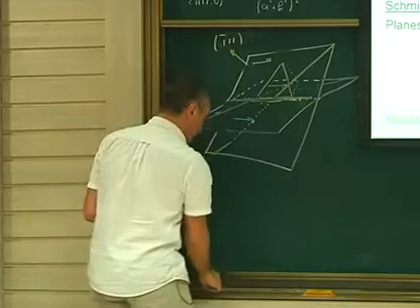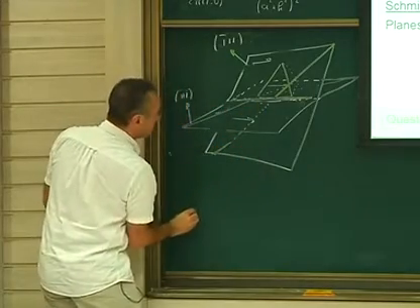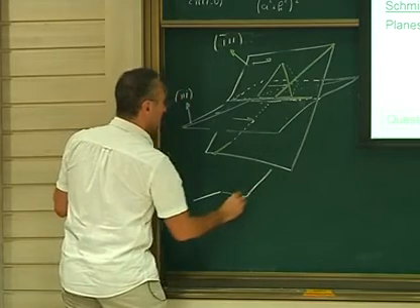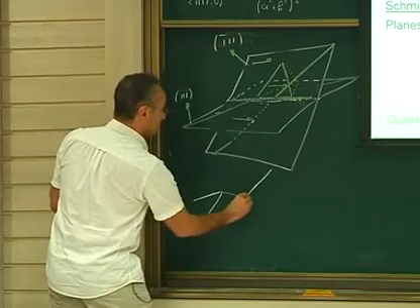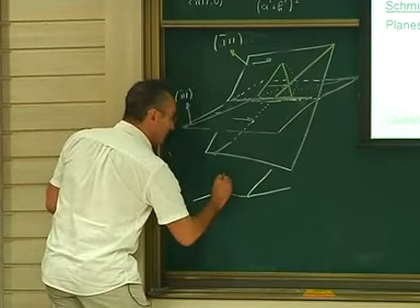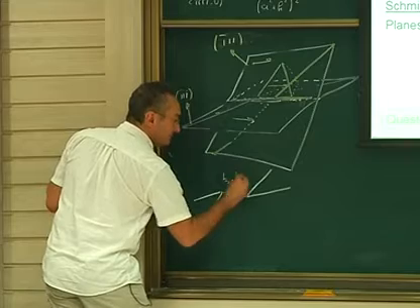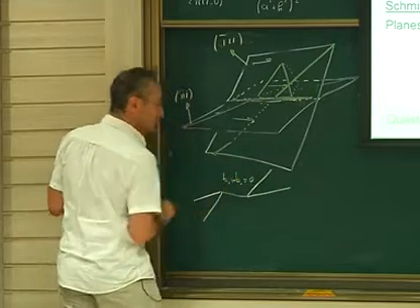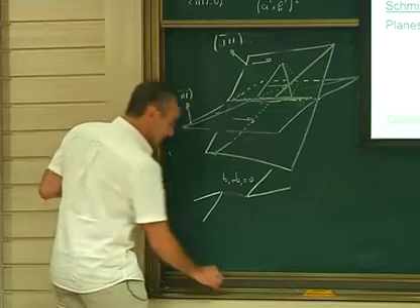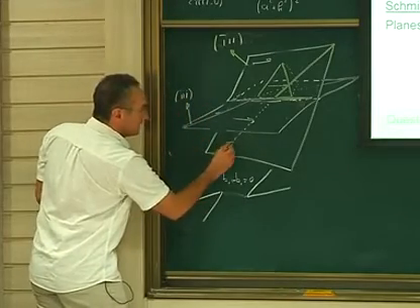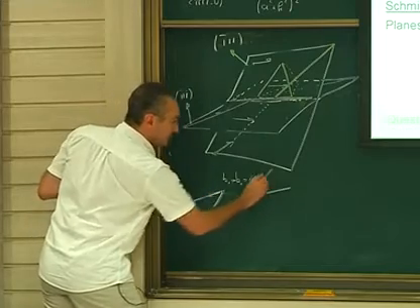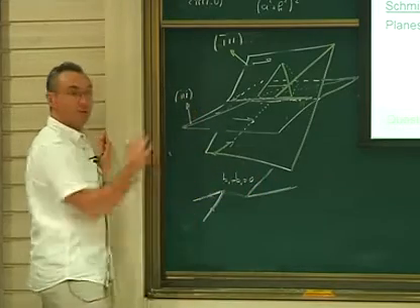when they cross, when they will meet, they will try to create a junction. This one is going up, this one is going down, this one is going on the back. This is my junction. But the junction now will be equal B1 plus B2, the same. So equal to 0, if you put a minus here. Okay. So this will be removed. You don't have the junction. So it means that your segment, which has a given orientation, will now be connected to its neighbor, and this segment will be connected here. So you have removed the part of the line.